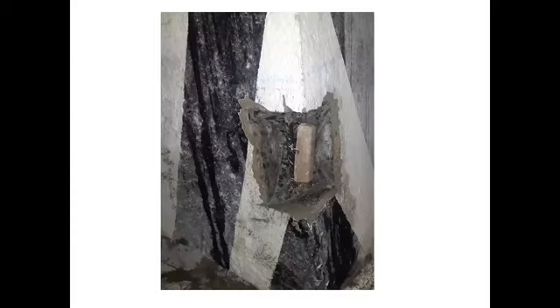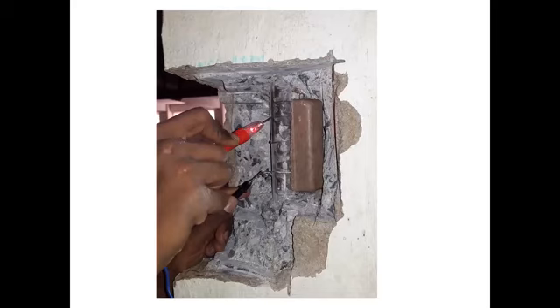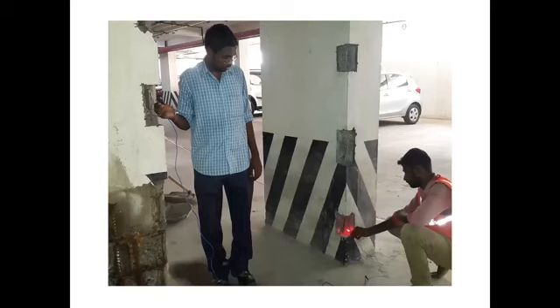So what you do is run the Profoscope, check where the main rebar is, chip off, and then space these anodes, tie these anodes, and check the connectivity between the anode and the rebar. The connectivity is very, very essential. Otherwise, these anodes will not function. In this particular case, you can see that in one of the columns an anode has been installed, and the connectivity between the rod and the anode has been tested in the other column.